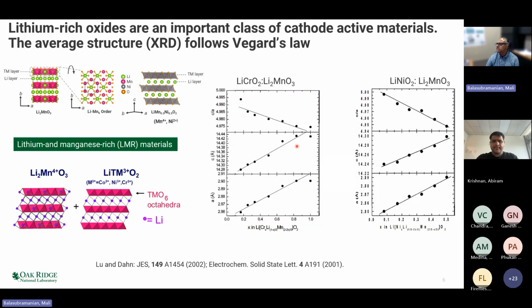And by Vegard's law, what we mean is that the solid solution that is formed between Li2MnO3 and LiTMO2 will have a lattice parameter that depends on the concentration of the transition metal in them. So if you use a composition that is in between, what you would see is that the lattice parameter would be appropriately weighted depending on the lattice parameter of the end phases. So Vegard's law is often found to be a very useful construct to understand properties of materials.